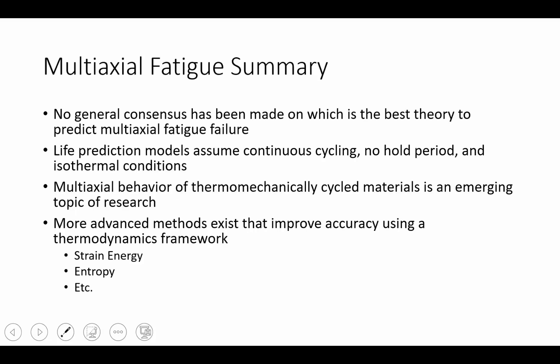Multi-axial fatigue summary: no general consensus has been made on which is the best theory to predict multi-axial fatigue failure. Multi-axial fatigue is still on the cutting edge even though there have been decades of work. Life prediction models assume continuous cycling with no hold period and under isothermal conditions. Multi-axial behavior of thermomechanically cycled materials is an emerging research topic — applying both thermal and mechanical loads either in-phase or out-of-phase. More advanced methods based on thermodynamics such as strain energy and entropy generation exist to improve accuracy.